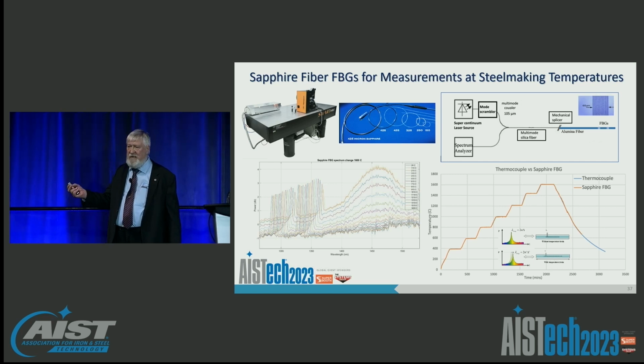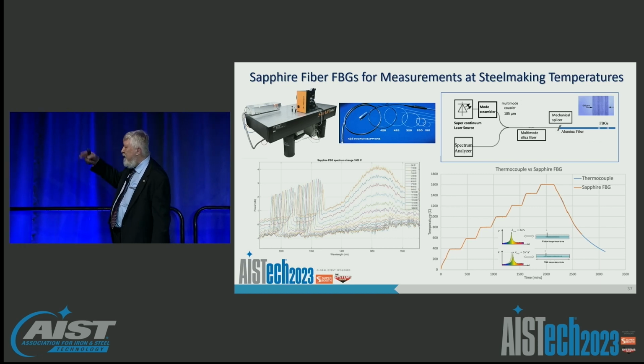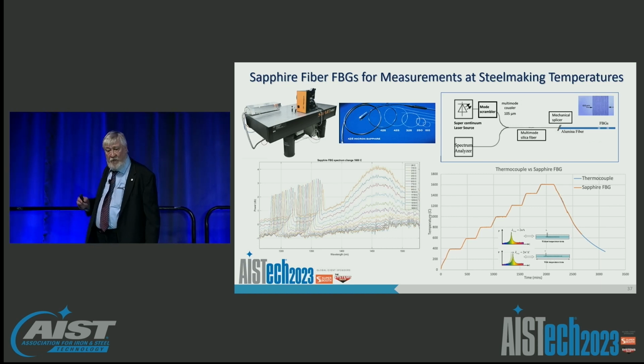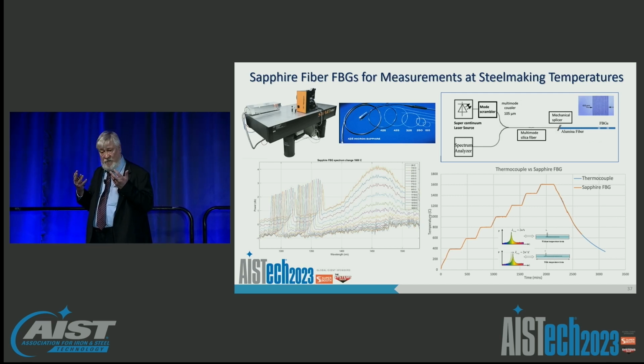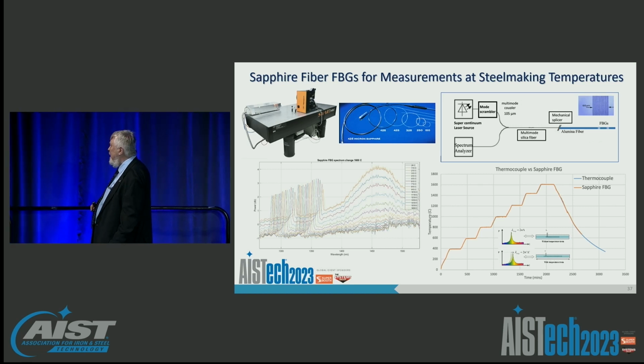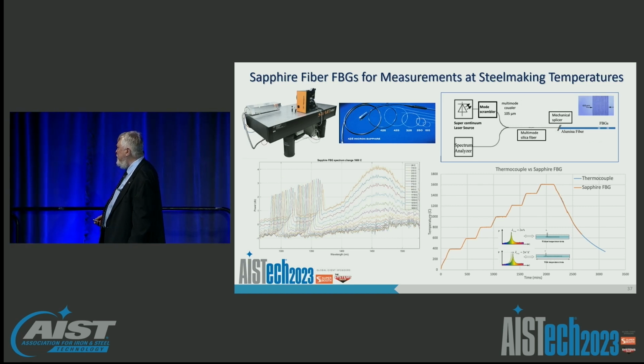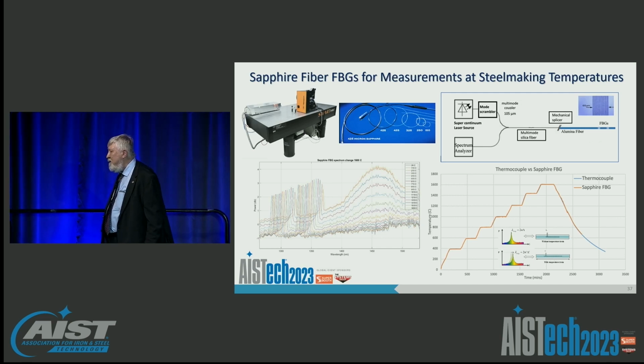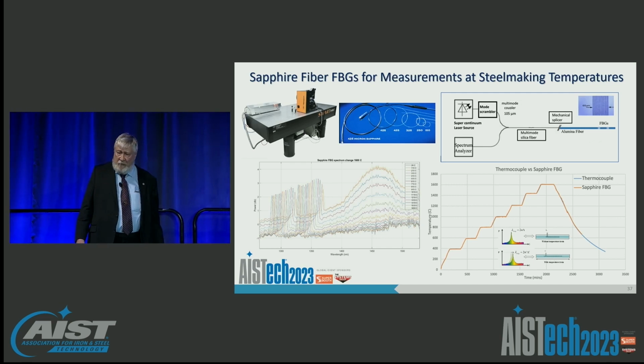We have to inscribe sensors. And so we use a femtosecond laser to put the lines in to create the Bragg gratings. We also use special mode scrambling technology to highlight the key signals we're most interested in. And with that technology, we've been able to demonstrate the ability to measure temperatures well in excess of 1600 C that you would see in most steelmaking environments. In fact, pushing 1850 C.